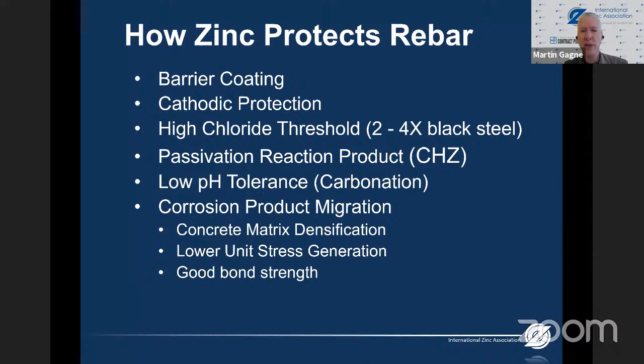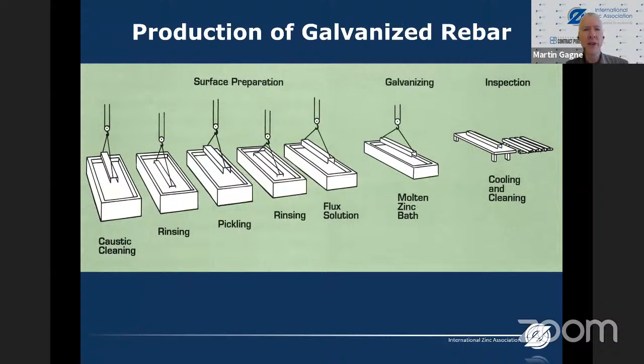We saw the corrosion product migration. So this has a number of benefits. It does not generate the stress at the interface, but it also densifies the matrix. So if there are chloride ions that are progressing towards the rebar, the concrete matrix now is more dense. It's harder for those elements to reach the steel. And there is indication that it does improve the bond strength of the galvanized reinforcing steel with the concrete as well.